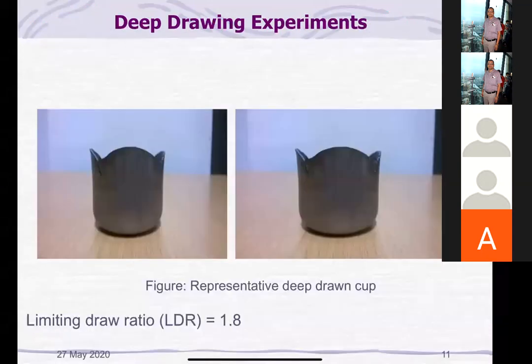These are some of the drawn components. If you see carefully, the ear height is quite high. It is primarily because the delta R value for this titanium is quite high. With titanium, there is another problem. Of course, at room temperature, the HCP structure is quite predominant. So at room temperature, the material is almost a brittle material.